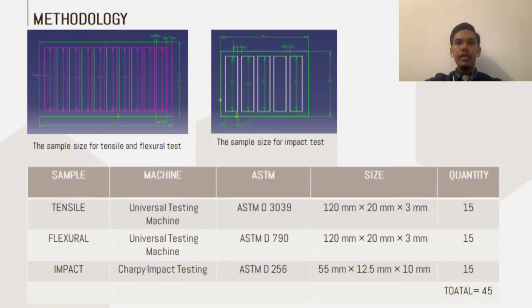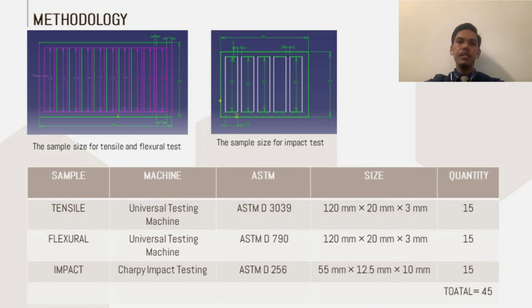Okay, this slide shows the standard size of samples that will be processed in this final year project. For the first picture, it shows the sample size for tensile and flexural tests. And the second picture shows the sample size for the impact test. For the tensile samples, we will use a universal testing machine in accordance with ASTM D3039, with 120 mm length, 20 mm width and 3 mm thickness. The quantity for tensile samples will be 15 samples for those 3 ratios.